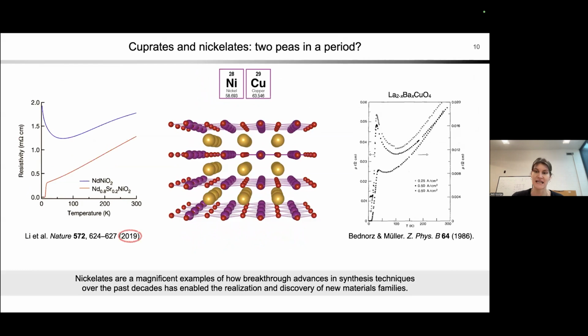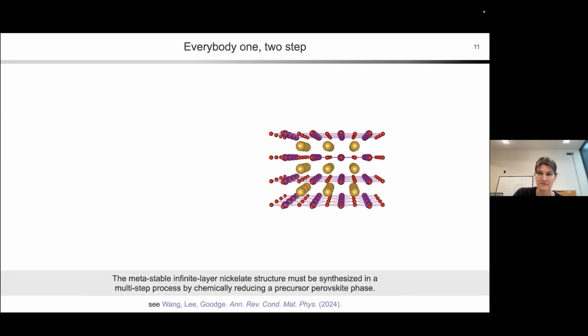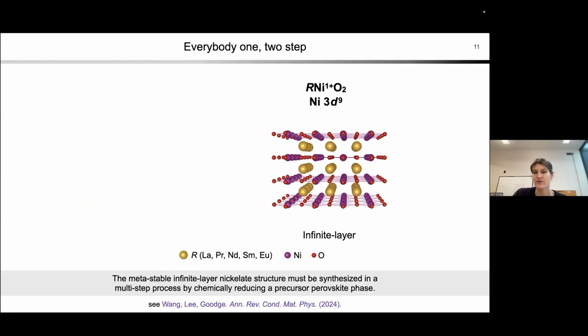And just to assure you, this is not for lack of trying, and it's not for lack of dedication or lack of talent on the people who were trying, right? It turns out to be an incredibly hard synthesis problem. The reason it's hard is because you want to get that same d9 configuration in the nickel, which means if you go backwards and count your electron valence, you need to have a monovalent nickel, or nickel 1 plus, right, to keep everything neutral.